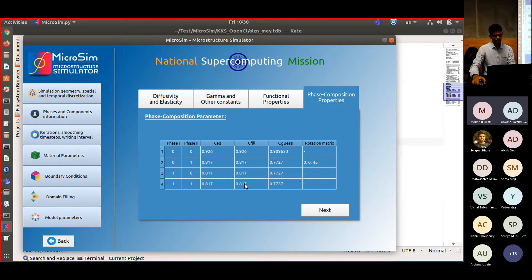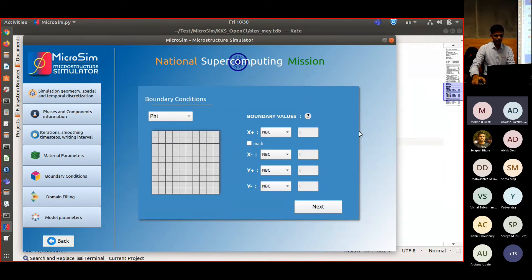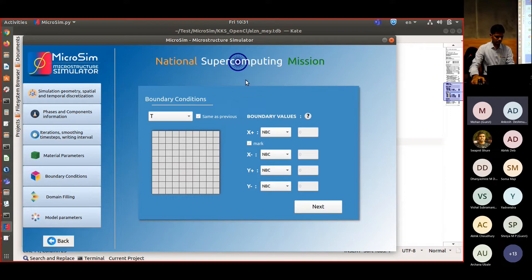The filling composition is used at the equilibrium temperature. The gas composition, C_gas, at the solving temperature provides a starting point for the iterative solution to get the phase compositions. We are using a rotation matrix with a rotation of 45 degrees. Rotation about the x-axis is sufficient for a two-dimensional system. For boundary conditions, we are using no-flux boundary conditions for all sites, all variables — phase field, chemical potential, and composition. We are doing isothermal simulation.